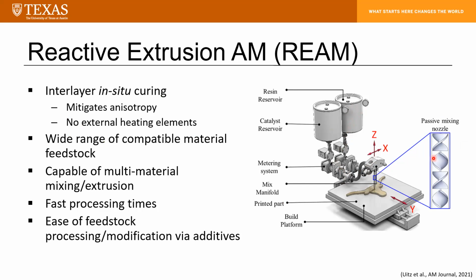So there are a couple benefits associated with this in situ curing. First, you mitigate anisotropy by promoting cross-linking between part layers. Additionally, there's no need for external heating elements, right? Because this isn't a melt extrusion process. It's not a sintering process. The only energy associated with running the system is the energy used to position your nozzle and to pump your materials. By using a two-part thermoset formulation, you sort of open the range of material properties that you can get from REAM parts by virtue of just having a wide variety of compatible material feedstocks.